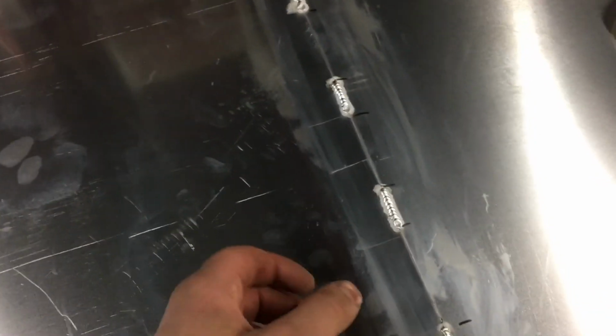It's going to create a bead. Your tungsten's going to start melting, and you're going to force too much heat into the aluminum and it's going to sink through. So something like this, I think I was sitting there for about 10 seconds, and this is 1/8 aluminum. So something thicker, you might have to sit there longer.